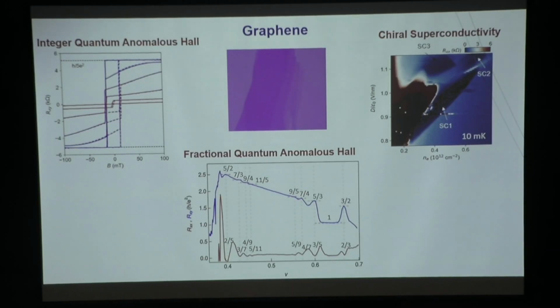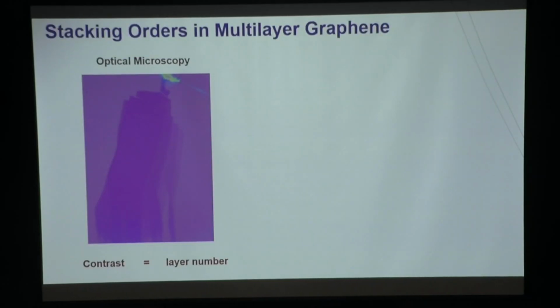Okay? So let me first tell you, what do I mean by finding correlation in graphene? Isn't graphene already very well known and people are so bored with it, so they start to do some twisting to give it a twist? Well, if you use tape to exfoliate from graphite, you get this random thickness that you can tell from your optical microscope image. The optical contrast basically tells you the layer number of the carbons you have there.